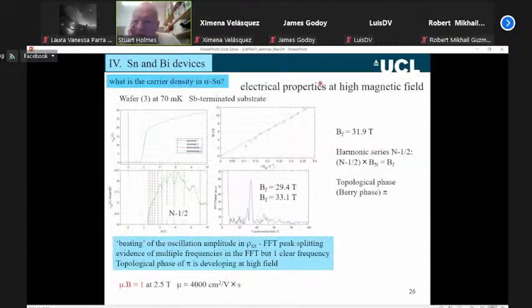So what happens at low temperatures? This was data I took in the summertime. This is now cooling a device down to 70 millikelvin. And this is device resistance now as a function of magnetic field up to 10 Tesla. What happens at low temperatures is we get some current going through the indium antimonide substrate, and then the indium antimonide substrate goes through this metal insulator transition that I discussed, and we're just left with the tin. And what we can see is magneto oscillations in the tin. This is due to the Shubnikov-de Haas effect.